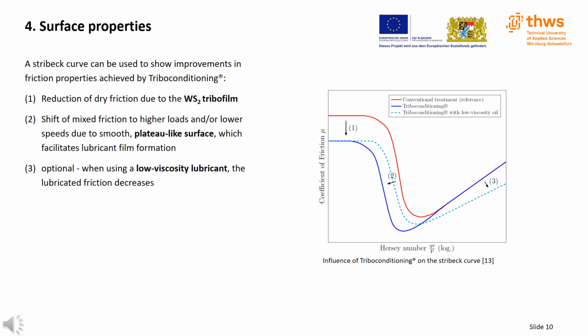The Hersey number is plotted logarithmically and is equal to the dynamic viscosity eta of the lubricant times the velocity v divided by the surface load p. The conventional treatment of a reference part is shown in red, a triboconditioned part is shown in blue, and a triboconditioned part using a low viscosity lubricating oil is shown in light blue with a dashed line. In the Stribeck curve you can see how triboconditioning improves the frictional properties.